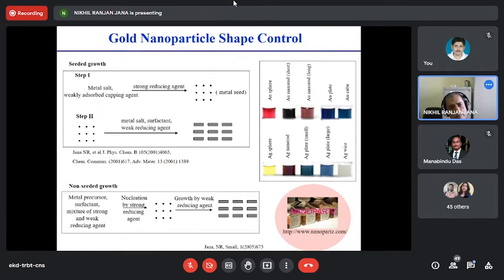If you want to make different shapes, these are examples. This is one of the approaches. If you want to make gold nanorods, first make a small spherical seed, then use some surfactant that attaches at a certain side face of the growing particles, so that the other faces will grow. This surfactant is a specific surfactant, CTAB, cetyl trimethyl ammonium bromide. It adsorbs at the surface, the side face, and the rod-like structure will grow. Because at the end faces, the surfactants cannot adsorb properly, gold will deposit at the two ends.